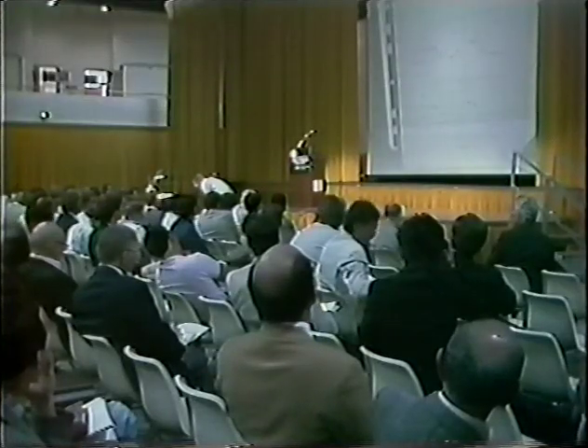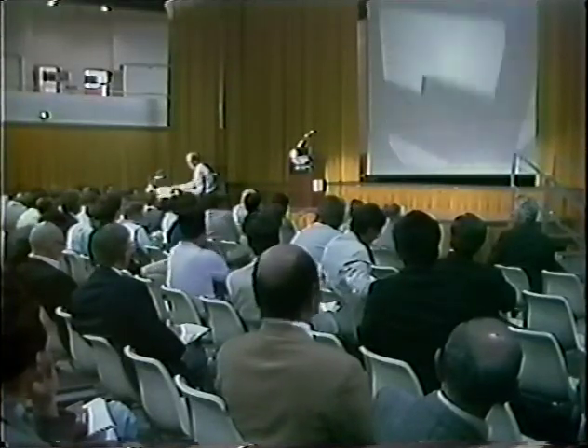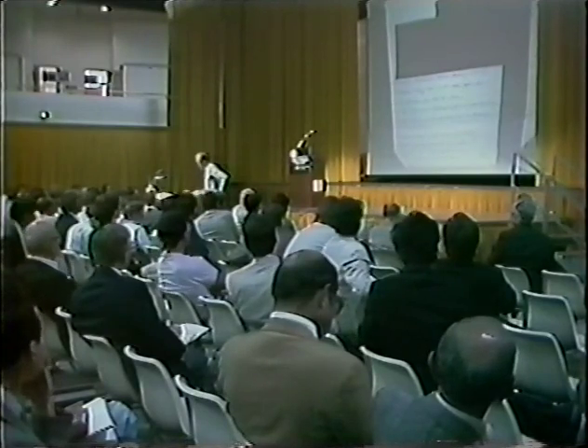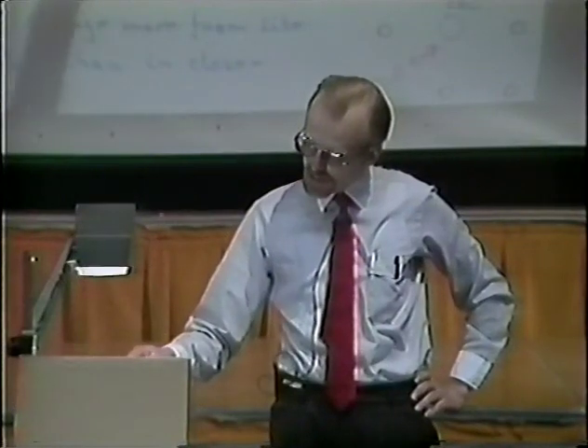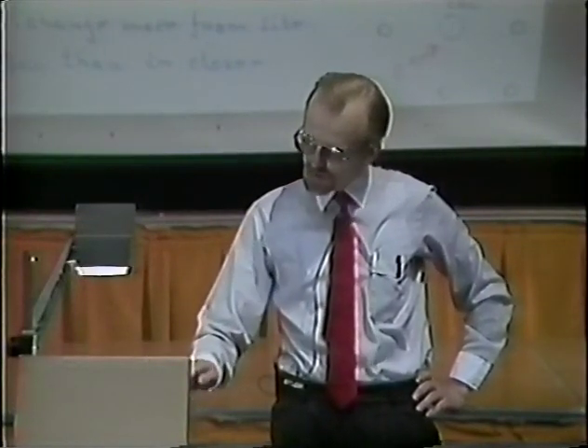Okay, so to summarize the content with the vacancy trapping, we can say that any dilatation will lead to a trap. A small dilatation you find for a dislocation or an interstitial atom, and thus you have a low binding energy of the order of 0.05 electron volts. For self-interstitials, which have larger relaxation volumes, you see somewhat stronger traps of the order of a tenth of an eV, and the strongest traps you have for vacancies and voids.